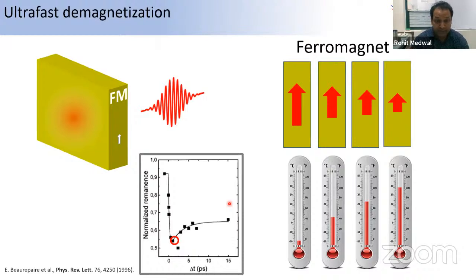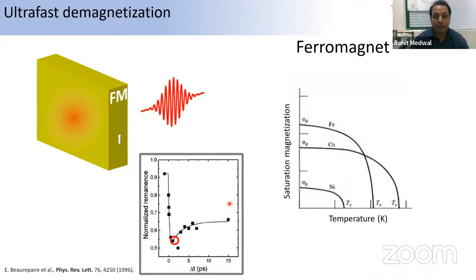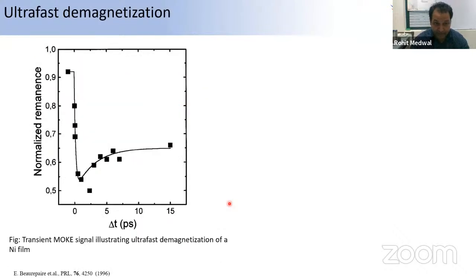But the question is, one can understand this easily. The question is how fast this quenching is happening. That is very interesting. The time scale here is 100 to 300 femtoseconds, depending on the material. At that ultrafast time scale, the quenching is happening. And this really drew huge attention from the scientific community, mainly the photonics community. People are trying to integrate the spin, because there is the magneto-optic community and the spintronics community, and they all merged together and made the spin photonics community. And they really got the attention of these results.